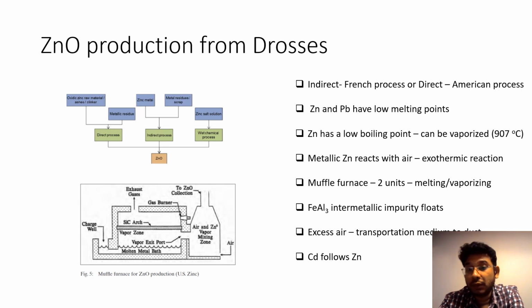And it boils down to this, very literally. Zinc has a very low boiling point, and it can be vaporized at 907 degrees Celsius. Most of the zinc recycling processes exploit this phenomenon. So whatever waste you provide them with in whichever form, what they would essentially do is heat it up to a really high temperature, at which point you have the metallic zinc being vaporized, and then you can collect it in one zone.